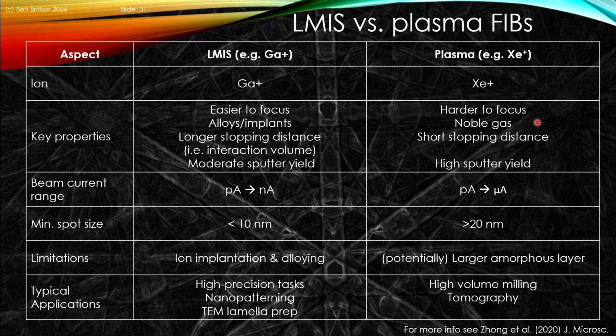It may implant, and you could get, say, noble gas bubbles in here. Because it's heavy and weakly interacting, you get a relatively short stopping distance. You also get a relatively high sputter yield, and so you can cut through a lot of material quite quickly. This is enhanced because we can now go up effectively 2 orders of magnitude, and we can use the FIB with microamps of current if we want.